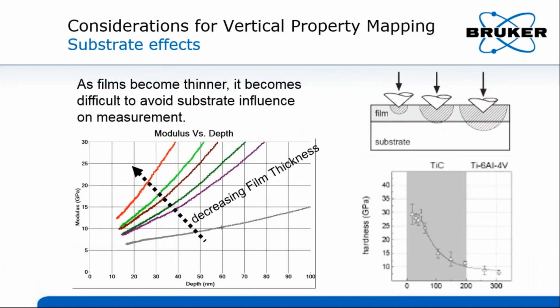Since the indentation measurement contains information about the deformed volume, indenting into a film-substrate sample is capable of detecting the information of both the film and the substrate. When the applied load is small enough, the penetration depth is small and the deformation zone could be within the film. In this situation, the collected mechanical properties could be contributed by the film only.